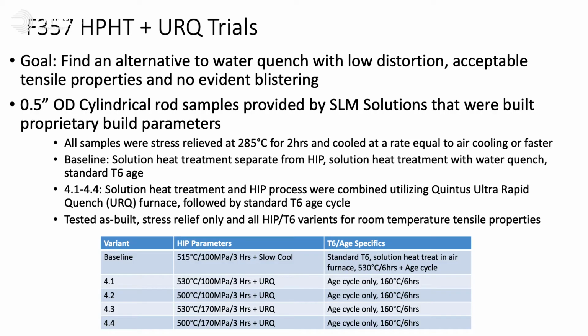Right, so you've been running different HIP trials with us now in our application center in Columbus, Ohio, using quenching technology basically at different HIP temperatures, and you've been looking at aging as well. So what kind of things have you come up with here? So what we really wanted to try were a couple of different variables, and we designed an experiment to look at different hold temperatures and different pressures during the HIP process. And then we just said, let's quench these things as quickly as we can within the HIP vessel. So we ran an experiment and then some baseline samples with the standard water quench and relief only that we're seeing used in industry. And then we did tensile testing to see what the results were.